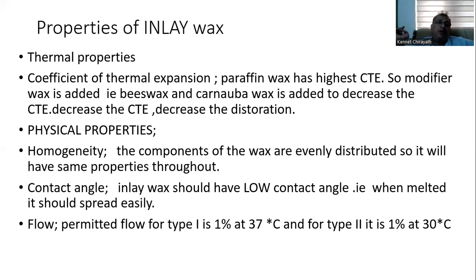The contact angle: the inlay wax has a low contact angle, so when melted, it spreads out easily. For flow, the permitted flow for type 1 is 1% at 37 degrees centigrade, and for type 2 it is 1% at 30 degrees centigrade.